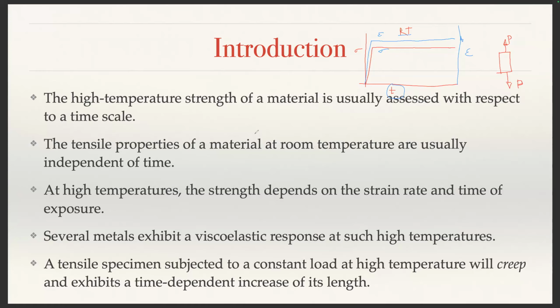Yes, sir. Now, but if you are not operating at room temperature, let us say I am operating at a temperature T1, which is greater than, say, 0.5 times the melting temperature of the material. Then what happens is, at this point the strain should have been constant, but because I am operating at very high temperature, the strain starts to increase. It will not remain constant. It will continue to increase. This is what we call creeping. That is the meaning of creep.